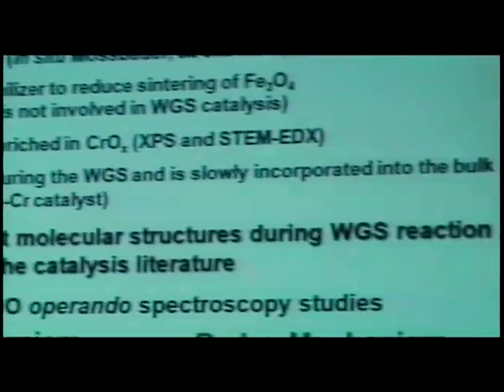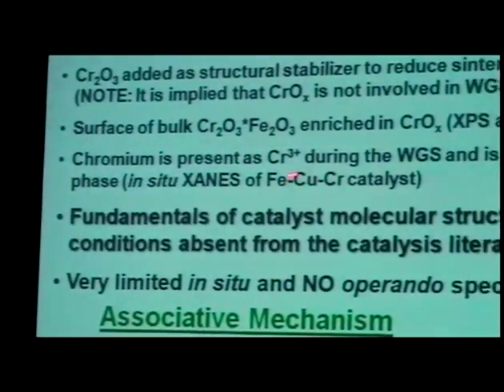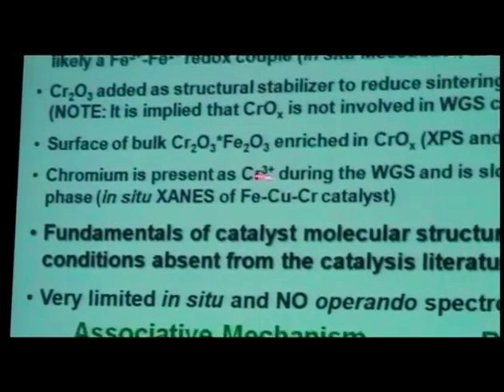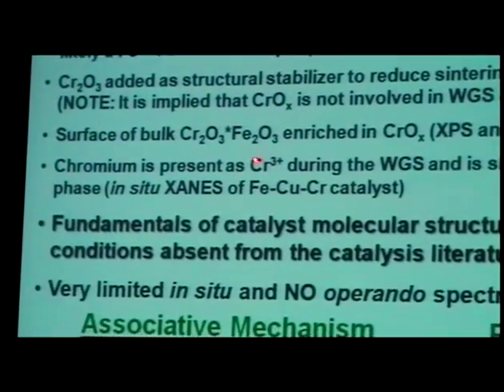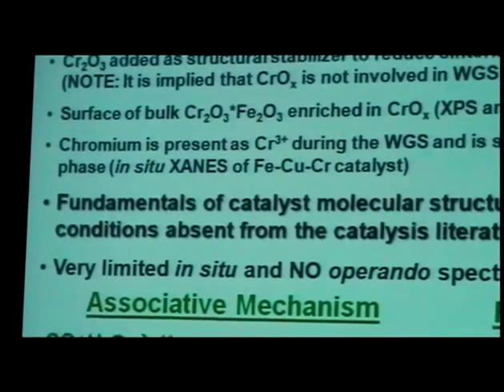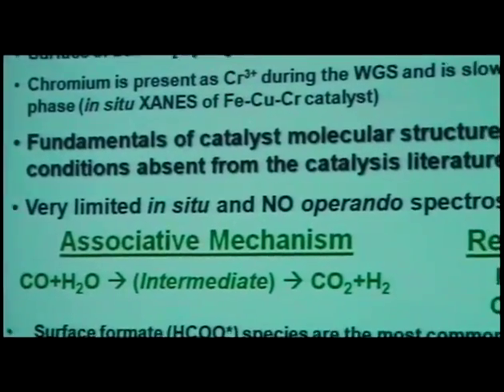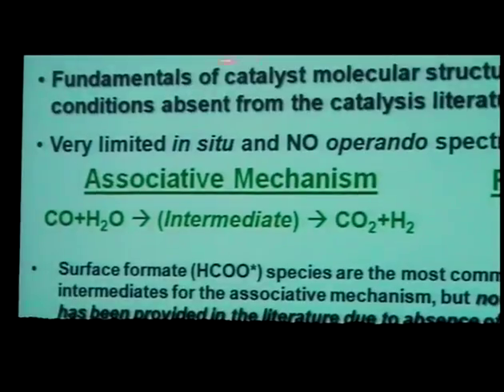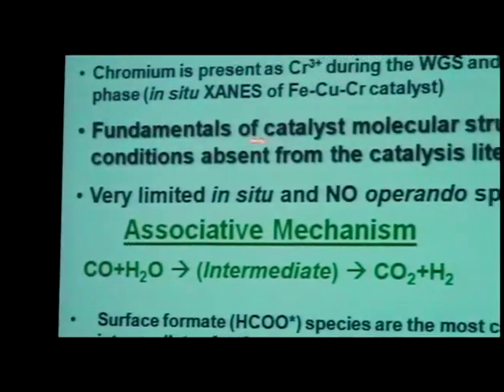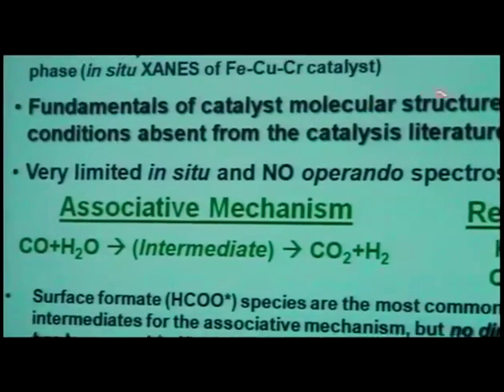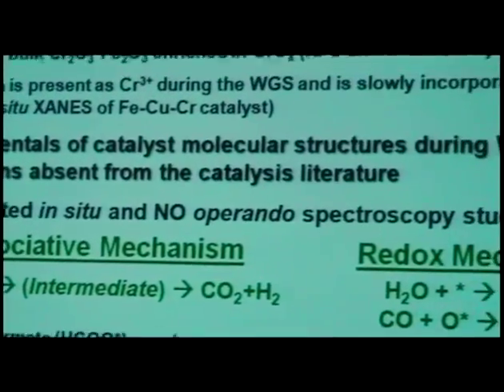Actually, this work done by Topsoe a couple of years ago was really the first in situ experiment that did X-ray absorption spectroscopy. They didn't look at iron chromium, but they looked at iron copper chromium, and their focus was really on copper. But they did indicate that the chromium was present as +3 during the reaction. And again, the paper did not really focus on the chromium. And if you look at all of this, there's really no fundamental catalyst molecular structure information during water-gas shift reaction conditions present in the catalysis literature, with the exception of this last recent publication.